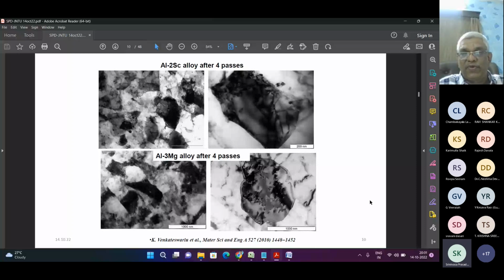Generally, what happens is after 4 passes, if you go on doing the 5th and 6th pass, there is no use. This is one Australian paper. You can see that they continuously did 8 passes, and they found that after 4 passes there is not much difference. So everybody restricts to 4 passes only. And when you are doing any grain refinement studies, according to the Hall-Petch equation, the grain size reduction influences the yield strength. That means the yield strength is enhanced when the grain size is reduced.